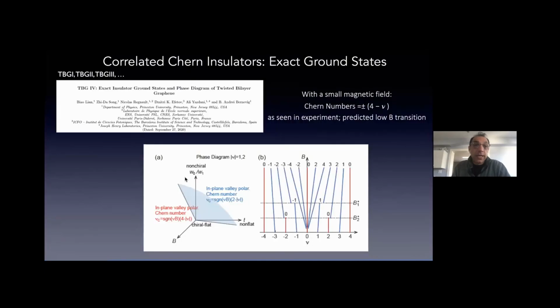All right, as was pointed out, there are exact calculations. Dimitri and I were dragged onto this paper with our theory collaborators, and the upshot is that there are many competing ground states. This is a very rich system near these integer fillings of 1, 2, 3, 4, and basically, as we apply a field, the understanding is that the high Chern numbers become favored. It just kind of makes sense. These high Chern numbers correspond to some orbital magnetism, which was just spoken about. So the magnetic field favors those states, and that seems to be what's happening, for example, near nu equals 3, 2, and 3. And the next interesting question is how these phases interact with superconductivity, which is what we're going to be aiming to understand next.